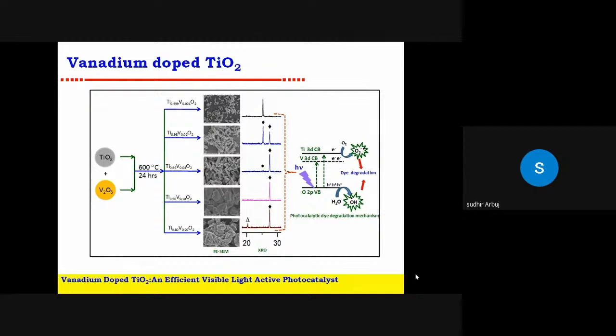So in this regard, we doped vanadium in TiO2 ranging from 0.1 mole percent to 20 mole percent, with other parameters kept constant, at 0.1, 0.2, 4, 10 and 20%. We observed nanoparticles getting rod-like structures and then aggregating to form larger structures. This change in morphology is due to the increase in the concentration of vanadium. Also, as we increase the vanadium concentration, the stability of the anatase phase decreases. The anatase phase is transformed completely into rutile phase above 4 mole percent doping of vanadium.